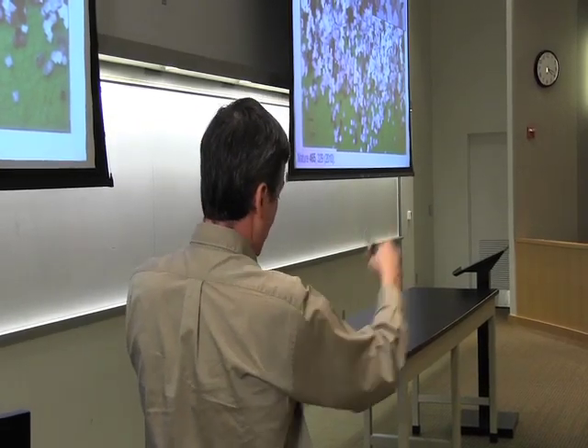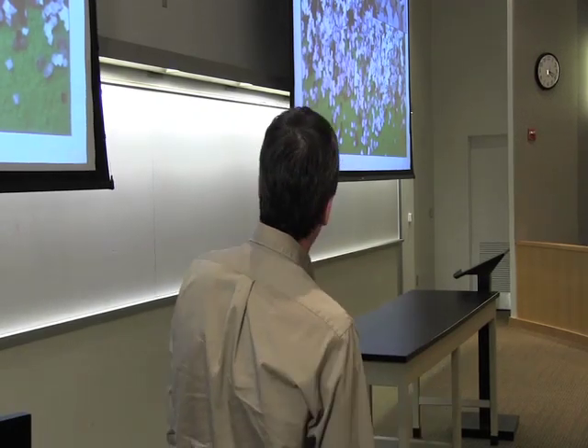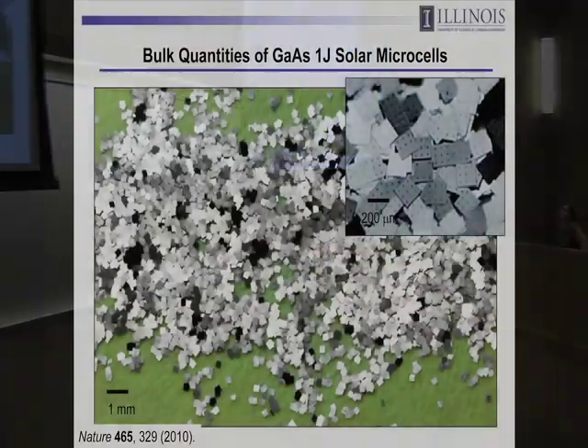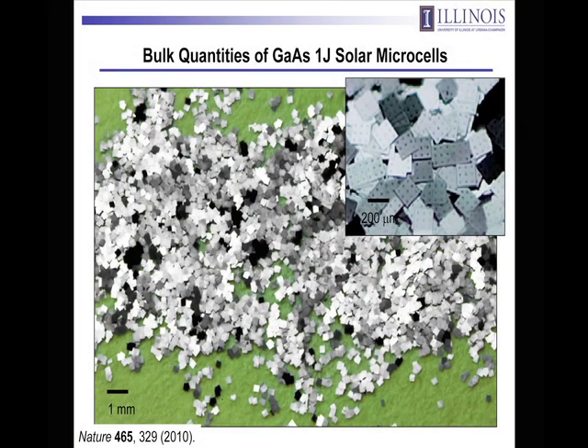This is what it looks like if you do that etching process: vertically etch down to define the lateral dimensions of the nanomembranes, release everything with the HF etch, and in this case, all the material comes off into the etching bath, and then you deposit it back down onto a sheet of filter paper. This is what it looks like: a bulk quantity of single junction gallium arsenide microscale solar cells. It's about 200 microns on a side, about 1 to 2 microns in thickness, depending on the design. And this is the kind of material you get out. So this is an idea in materials that I think is compatible with those ideas in mechanics.